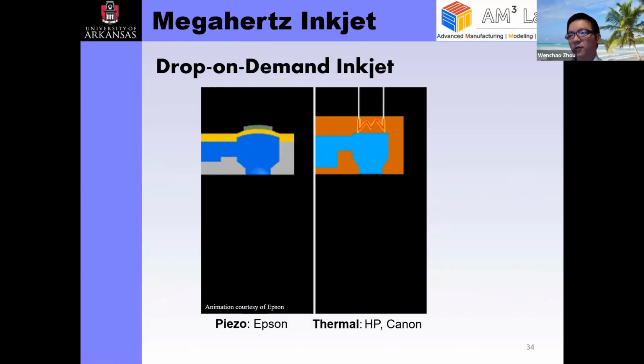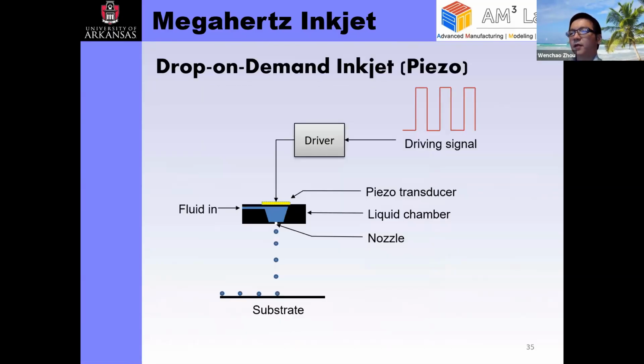The way that it works is that you give a driving signal to a driver. Whenever you give an electrical pulse to this piezoelectric transducer, it will deform, and the deformation will cause the droplet to be jetted out. You give one pulse, it generates one droplet. So it's drop on demand. By controlling the way that it goes to the substrate, you can print patterns.